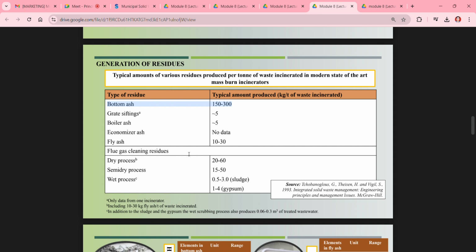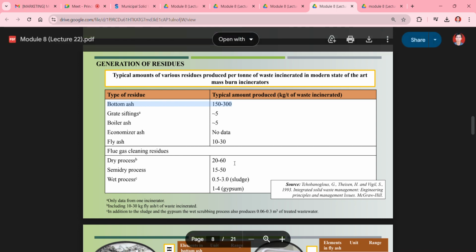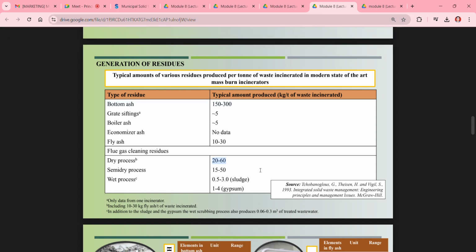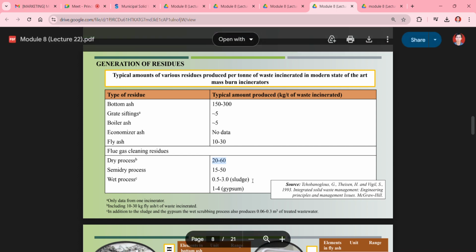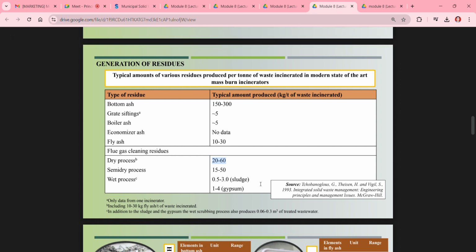And then coming to the flue gas cleaning residue, the dry process can produce flue gas cleaning residue of around 20 to 60 kg per ton, because it will also contain the amount of calcium hydroxide or sodium bicarbonate provided as a dry source to catch the flue gas or to neutralize the flue gas. Then the semi-dry process can produce around 15 to 50 kg per ton, and the wet process can produce around 0.5 to 3 kg per ton of the material in the form of sludge or in the form of gypsum.